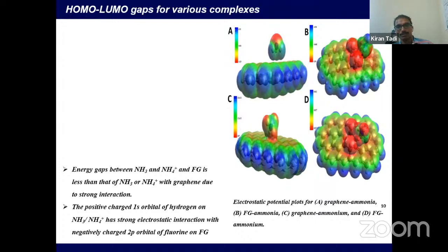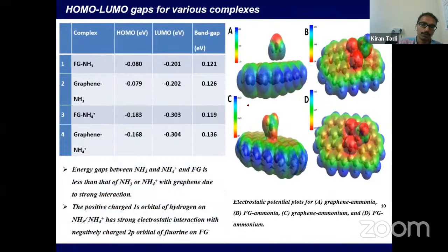But here my molecule is specifically attaching to the fluorinated graphene, whether it is an ammonia molecule or ammonium ion, whether in liquid or solid. So there are specific interactions between the ammonia molecule and the hydrogens and fluorine molecules here. There is some electrostatic interaction, and the band gap has also decreased in this case. This is 0.119 here, this is 0.121, whereas for the graphene it is 0.126, and here for graphene ammonium it is 0.136. So you can see there is a close interaction between the HOMO and LUMO, and that's because of the specific interactions we found here.